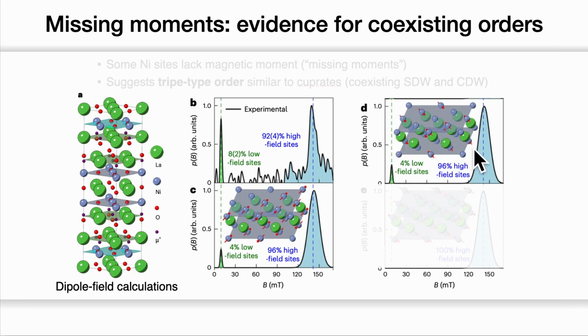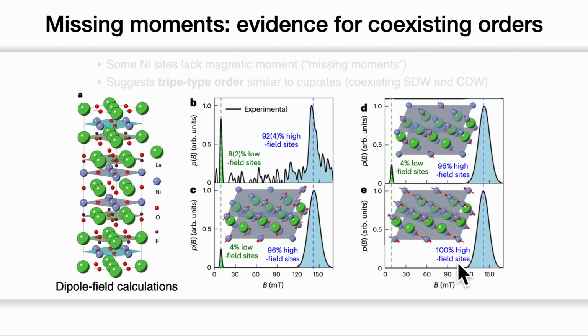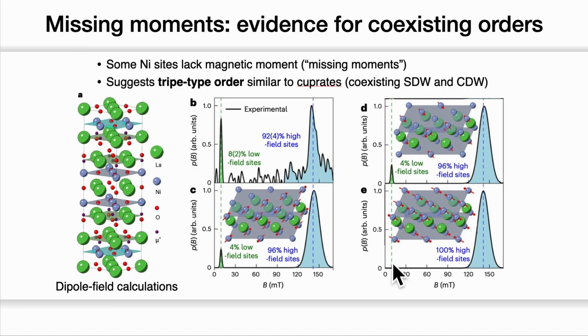Here, this is another pattern with missing magnetic moments, which also reproduces the experimental data. However, if there are no missing magnetic moments, then we cannot reproduce the experimental observation. So this suggests a stripe type spin density wave in this material, like a cuprate.